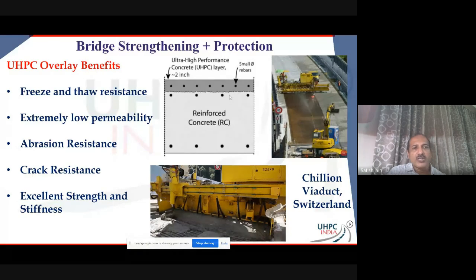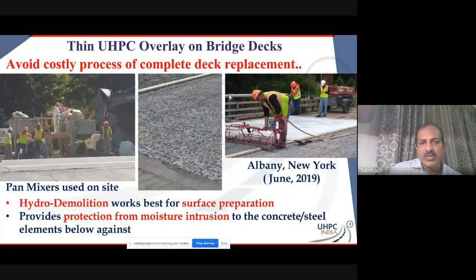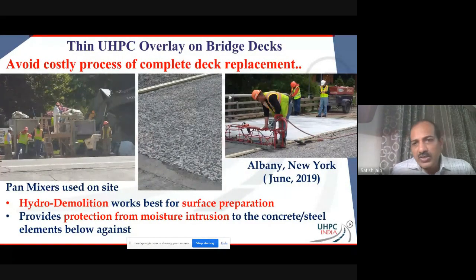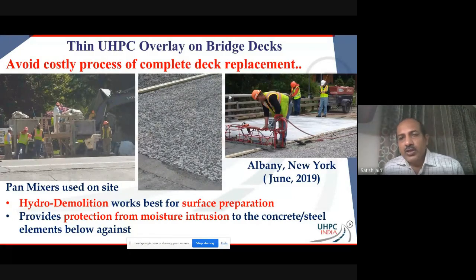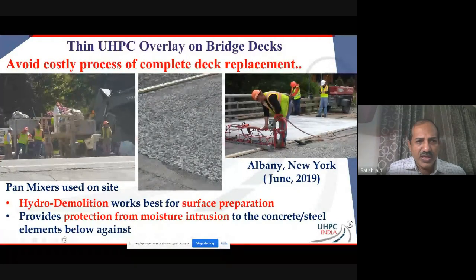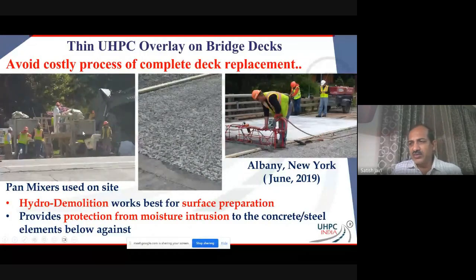So you get advantage in terms of freeze and thaw, very low permeability, again, abrasion resistance, I spoke about it, crack resistance, excellent strength and stiffness. You mention it, it's there, correct? And you just get excellent behavior throughout the life cycle. Here is something that I saw in person. This was in 2019 in Albany, New York. UHPC is just mixed on site in a bit of a high energy pan mixer. So it's not just a simple pan mixer. There's a bit of a high energy pan mixer that they've used.